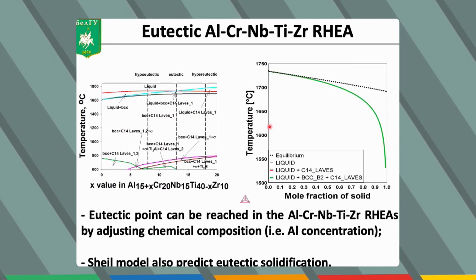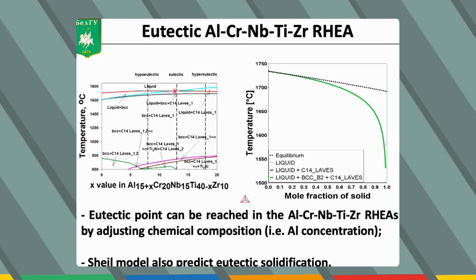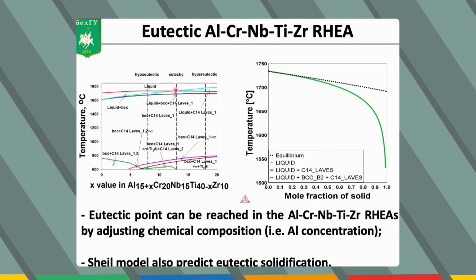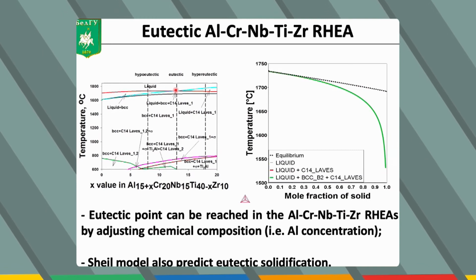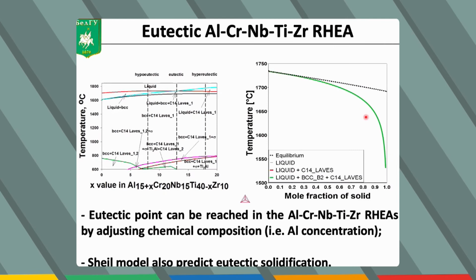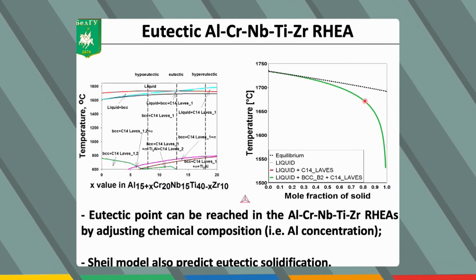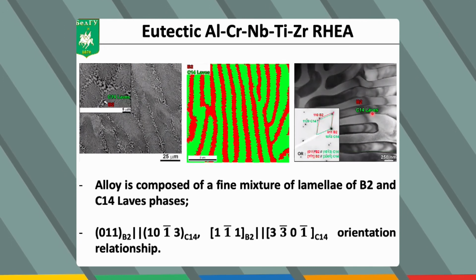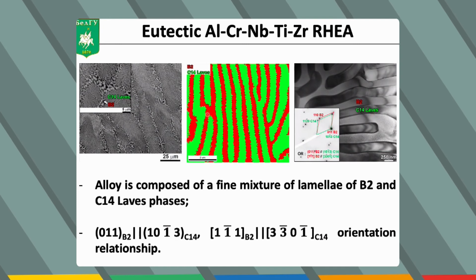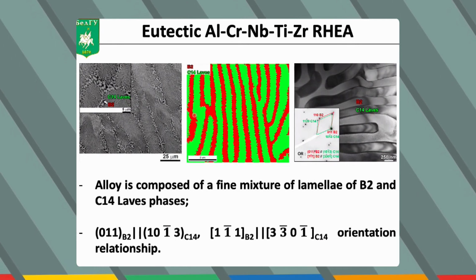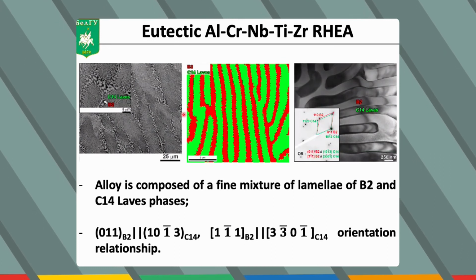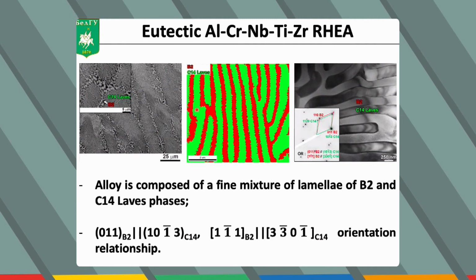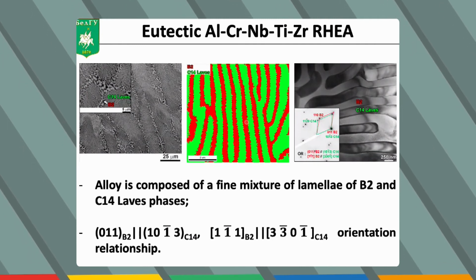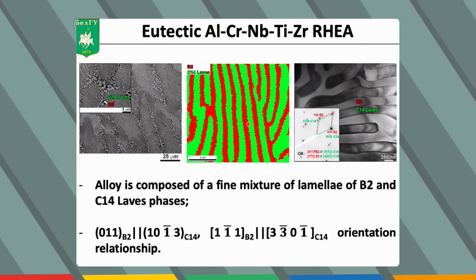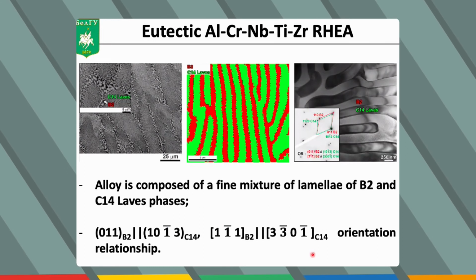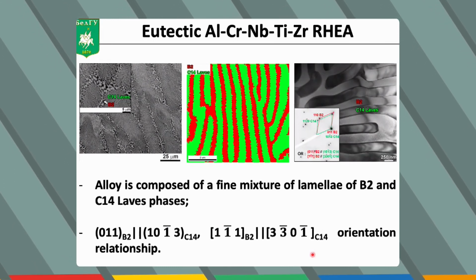But there were a number of steps before, and you can see quite clearly here the eutectic point where the Laves phase and the B2 phase precipitate simultaneously from the liquid, and these solidification curves also confirm it. And of course we fabricated this alloy experimentally. And we got a very fine, very nice eutectic microstructure composed of thin lamellae of B2 phase, you can see it in red here, and Laves phase, you can see it in green. No other phases can be found, and there is a specific orientation relationship between these two phases. I think this type of orientation relationship between these two phases has never been reported so far.